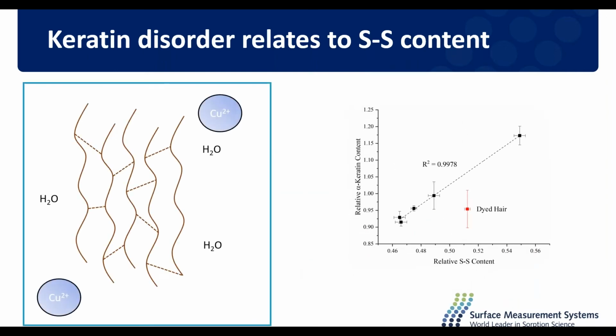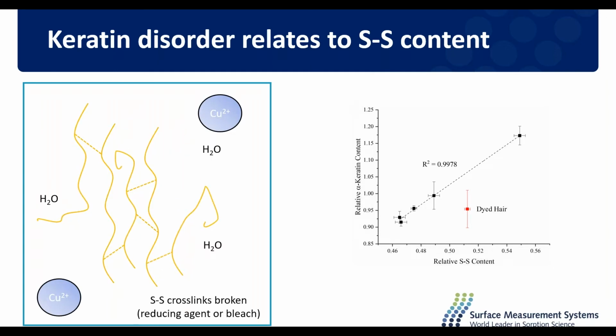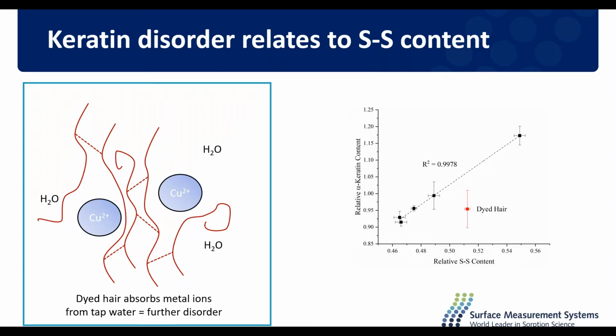I've got here just a little figure to try and explain, and we've got our keratin molecules with the disulfide bonds between them in dashes, and this is in tap water, so we've got some metal ions around there as well. Now, when we break our bonds, this is either through bleaching for the dyed hair or reducing for our reduced hair samples, we're increasing that disorder, and that's what we would expect with the reduction of these bonds. But with the dyed hair sample, we have an extra step. And this is because in dyed hair, it's been very well established in literature, it absorbs far more metal ions from tap water than untreated hair alone.